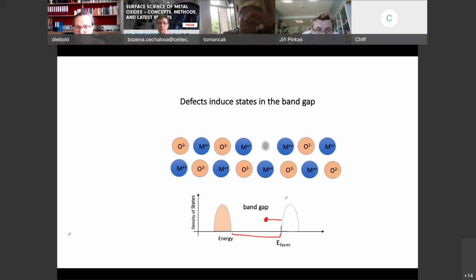The reason is we have these oxygen vacancies here. So you take out an oxygen, right? I told you in the beginning, oxygen has 2 electrons. You take out a neutral oxygen, it leaves behind 2 electrons. And these 2 electrons actually like to go down. We can tell from our images together with DFT calculations that these 2 electrons like to sit not on top of the surface, but on a titanium atom in the next row below, underneath. And these electrons can hop from one to the next, to the next, to the next. That's the conduction mechanism.